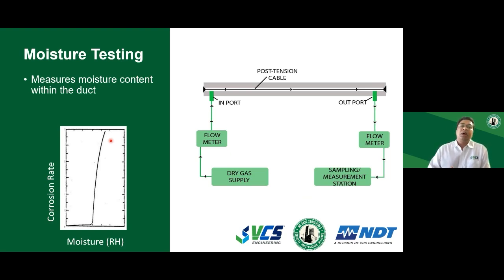To measure the relative humidity inside the duct, we use something called moisture testing, where you drill into the concrete, you drill into the duct and you make maybe a ½ inch or a ¼ inch opening, and you have an input, you have a similar output, you have a flow meter, and you try to push a dry gas through the duct. Essentially, we are trying to measure what's the relative humidity inside the duct using a dry gas.